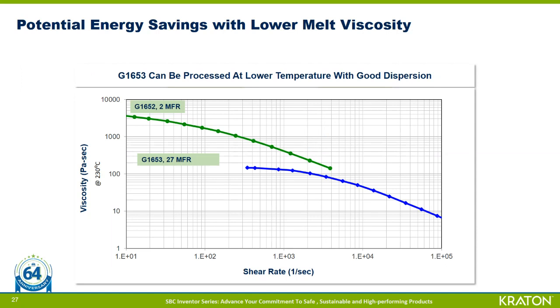Next, we have a rheology plot that reflects the step changes in viscosity and shear rate between both G1652 and then a lower melt viscosity product such as G1653. So typically lower viscosity at higher shear rates are preferred and may offer potential energy savings due to less energy input needed to mix the low viscosity products. So on the previous slide, we were looking at a solvent-based system, and on this particular slide, this is a hot melt-based system. So in this case, G1652 has a melt flow rate of 2, while the lower viscosity or the higher melt flow product of G1653 is closer to 27.